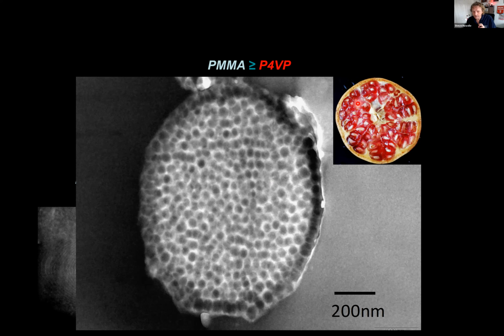So we could change the structure. And you can see here that we're working with a particle that's of the order of 1 to 5 microns. And we have domain sizes here that are on the small nanometer scale, so around 20 to 50 nanometers. And we're engineering that by changing the block copolymer chemistry.